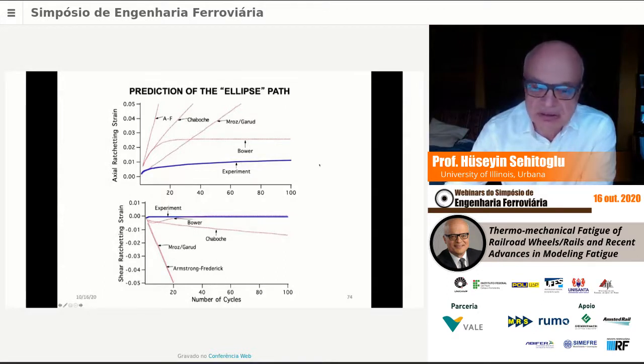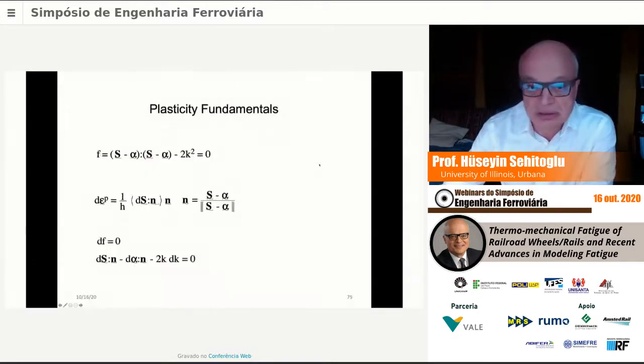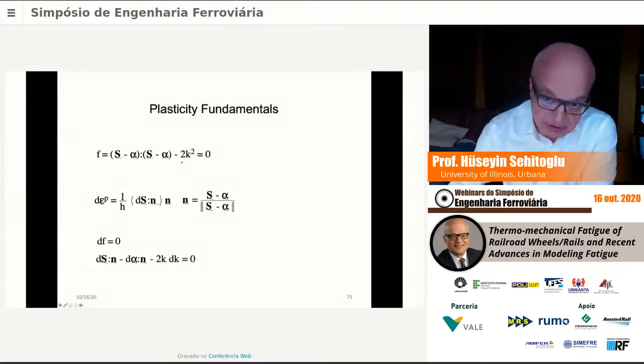And you can see that these models are just over predicting the ratcheting. They're predicting very high ratcheting. Ratcheting rate decreases with cycles, as we see. We need a model to capture that.